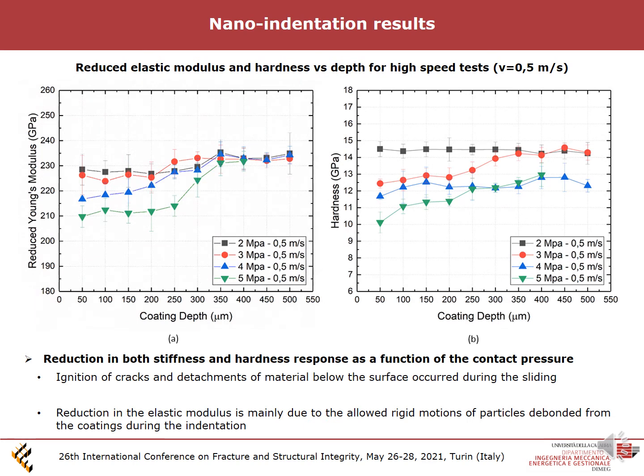On the contrary, nano-indentation measurements carried out on the coatings tested at 0.5 meter per second show a significant reduction in both elastic modulus and hardness response as a function of the contact pressure.